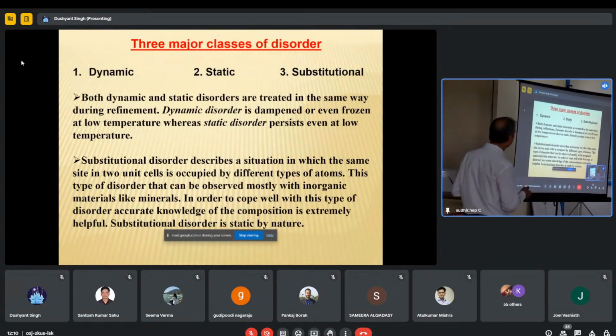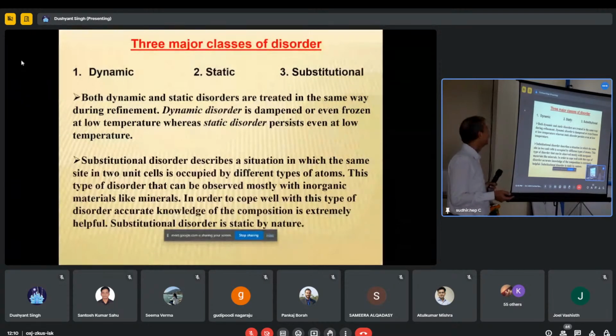Three major classes of disorder are dynamic disorder, static disorder, and substitutional disorder. Dynamic disorder we can solve by taking data at low temperature, as nowadays almost every diffractometer has a low temperature facility. You collect data at a low temperature, dynamic disorder is taken care of because vibrations will be very, very less and your disorder component will not show more than 5% disorder. But substitutional disorders are mostly static kind of things.